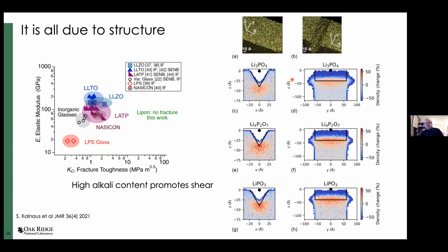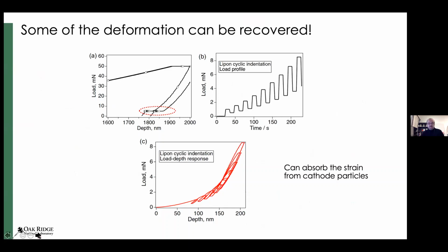But what is clear here is that the material with the highest concentration of lithium or alkali ions in the system exhibits most of the shear deformation. And this is exactly, so we have 3 lithiums per 1 phosphorus. So this is exactly what we have in LiPON. And the take-home message is that high alkali content promotes the shear in this material. And again, no fracture has been observed, at least under these loads and these strain rates.